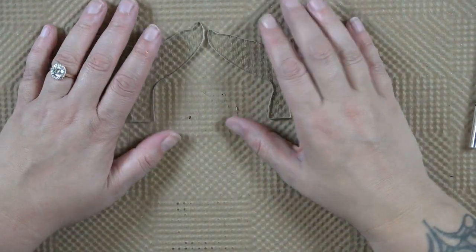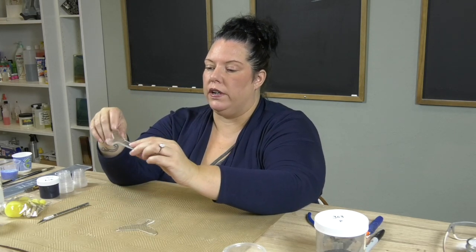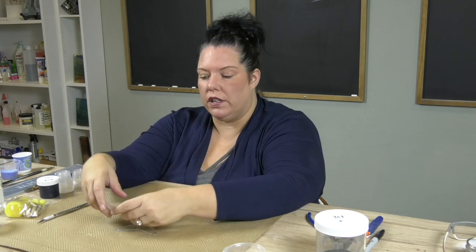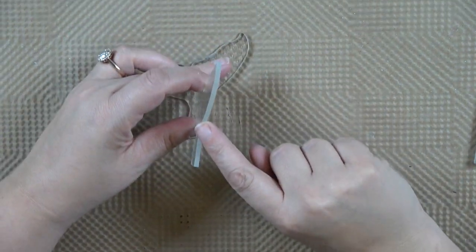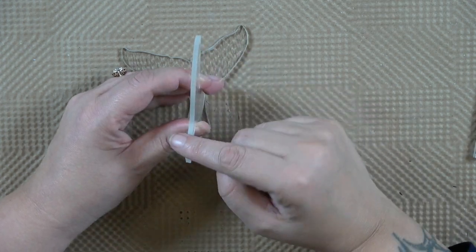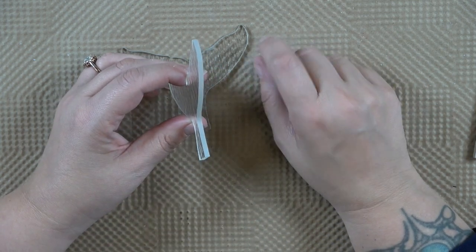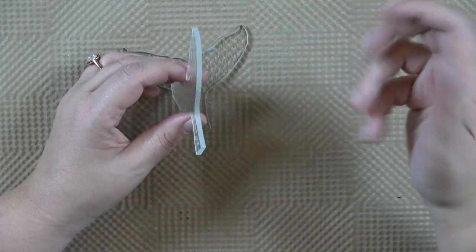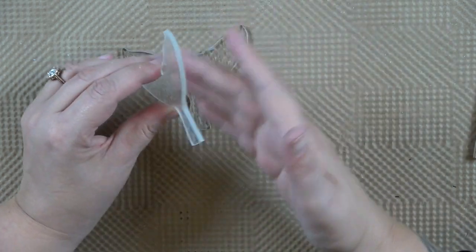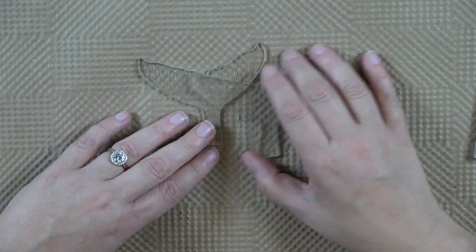Now guys, something else that's important, when you get these water jet shapes, and we've got about 20 new designs of them, you want to clean these thoroughly. Just take an alcohol and water solution and clean them. Reason being, the water jet machine will come around and cut it, and it can leave an oily residue on your piece, and you can get your devitrification or some of that residue to actually fuse into your piece. We discovered that when we got so excited, ripped them open, and went, oh shoot. We haven't had any problems since, but clean these, not just the tops, but the sides from the water jet machine. So I've got 2 whale's tails here, and I'm just going to paint 2 at once.